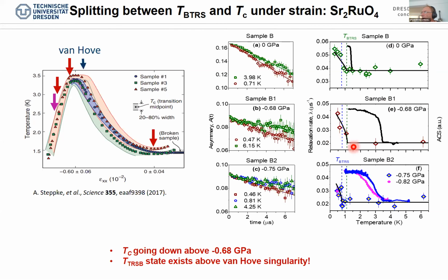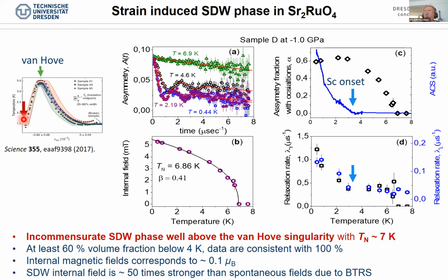But now at the maximum, at one strain point here, which is -0.75 GPa and -0.82 GPa, it looks like there is some reduction of the time reversal symmetry breaking temperature. But still, I want to point out we are above the Van Hove singularity, and there is still time reversal symmetry breaking and no spin density wave or other kind of magnetic order. So we are right now here. But if we go to our maximum uniaxial pressure, which we could apply, which is roughly about 0.85 gigapascal, no, 1.0 gigapascal, sorry, minus 1.0 gigapascal, then the spectra completely change.